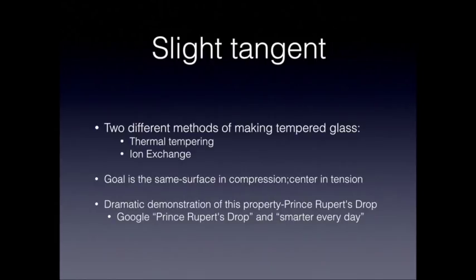In either method, the goal is the same: you want to create compressive forces on the surface of the glass, and tension in the center of the glass. This is the underlying principle behind tempered glass, and there is a really dramatic and fascinating demonstration of this property available on the web.